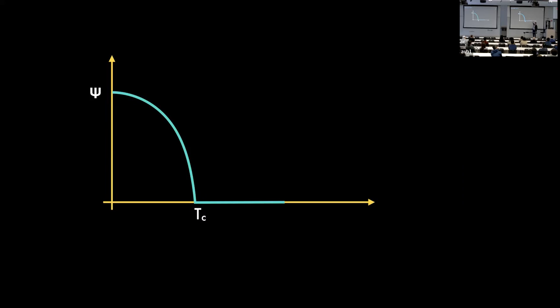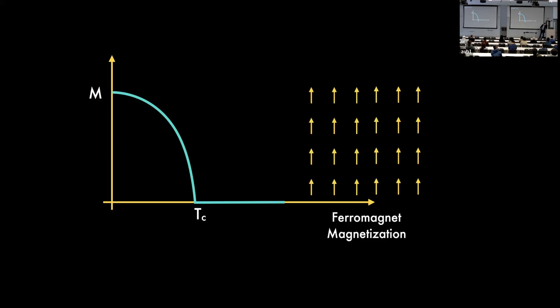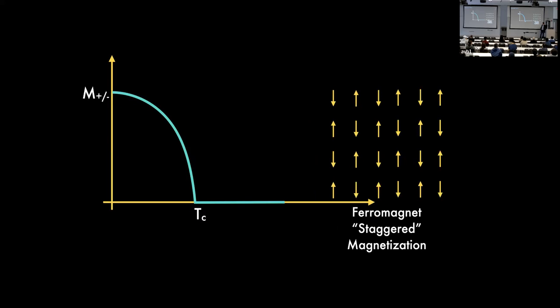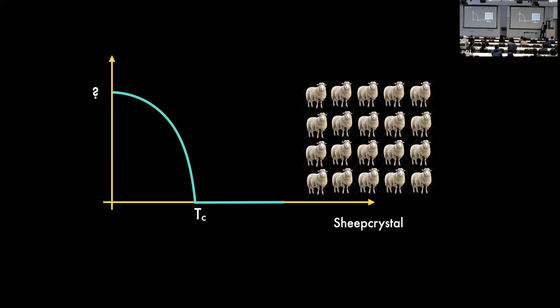But at temperatures higher than that, the thermal energy is much greater than those interactions, and the system isn't able to order at all, or those spins aren't able to see each other anymore, or those sheep aren't able to order anymore. In the case of a ferromagnet, this would be magnetization, and what you might see is that you have 0 above its critical temperature, and then that magnetization would grow as you go to lower temperature, and that would be something that you could really measure in a material as you cool it down. And an antiferromagnet would be the staggered magnetization, and whatever it is in our sheep crystal.